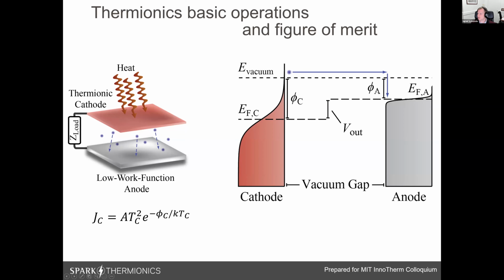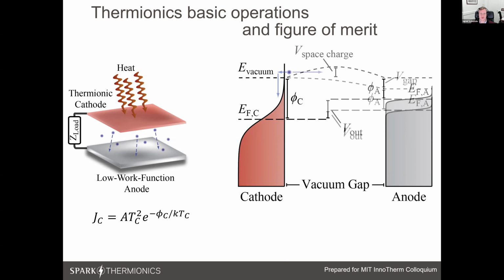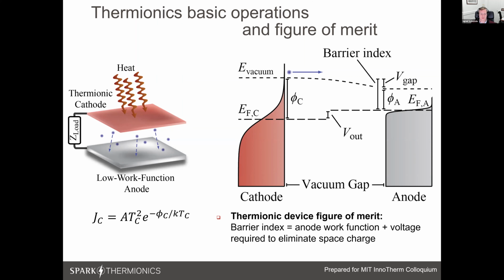However, in reality, electrons have charge. And so once they begin to emit into this vacuum gap, there's typically some amount of space charge that builds up that begins to suppress that emission current. That means that you often have to apply some accelerating voltage within the gap in order to mitigate that space charge. And that brings us to the basic figure of thermionic devices, which is the sum of the voltage within the gap, as well as the anode, sometimes called the collector work function. So this is known as the back voltage or barrier index.